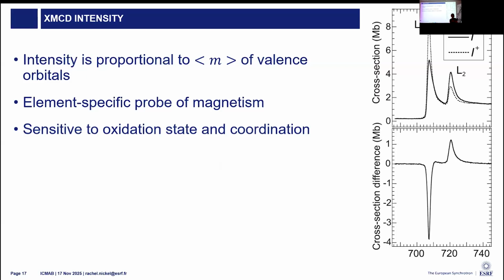So for a case of a simple oxide, say magnetite, where you have trivalent and divalent iron that's in both tetrahedral and octahedral coordination, you do see the shifts in the spectra, and you can identify the contributions of each site using XMCD versus something like XAS, where they're all positive magnitude, and so it's a little bit more difficult to separate.